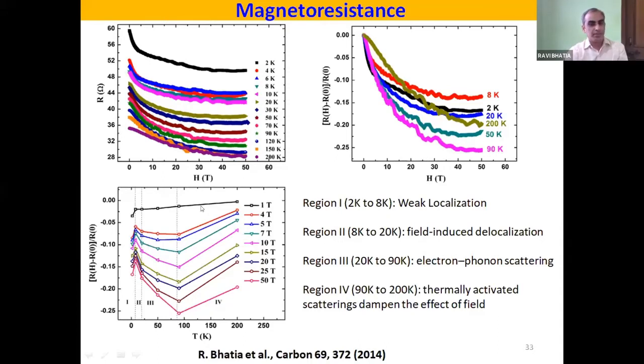So this gives rise to the feeling that there is a magnetic field induced delocalization from 8 Kelvin to 20 Kelvin, which has a different slope than the next region. I still don't want to go into details of this, but I want to say one line: at the lowest temperature, you should see maximum negative MR. At the highest temperature, one should see the lowest MR. But why, when we plot in terms of magnetoresistance, does it not present a trend with respect to temperature and magnetic field, which can be understood by plotting the whole data in this manner.